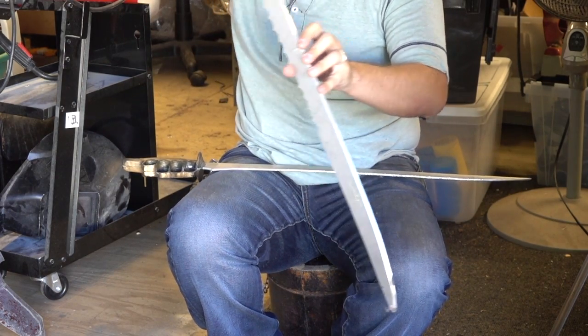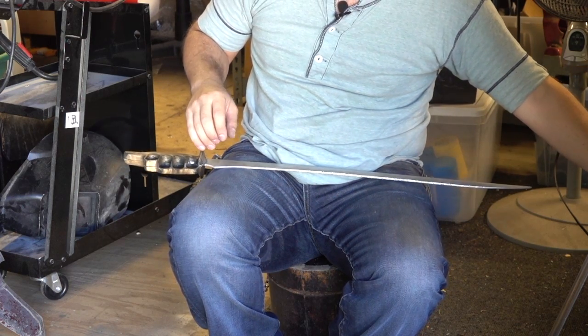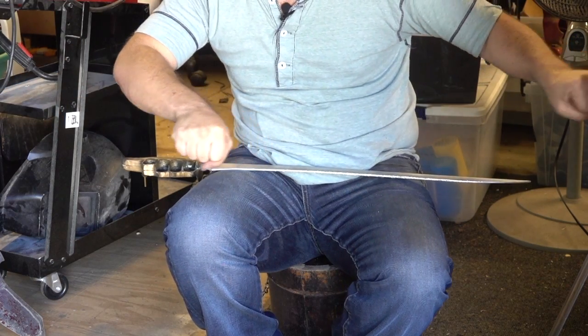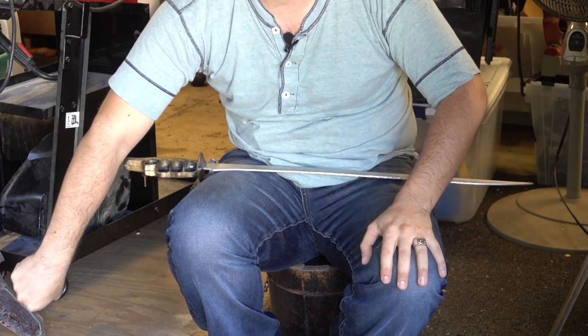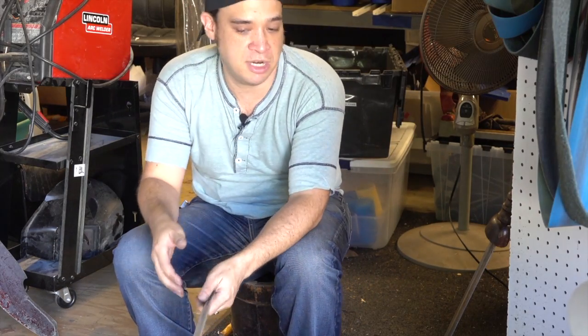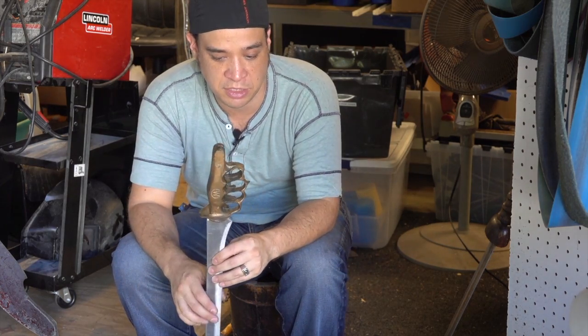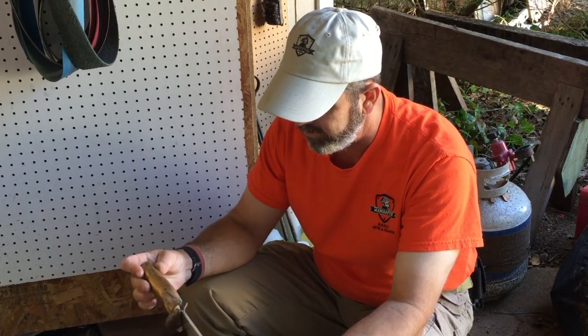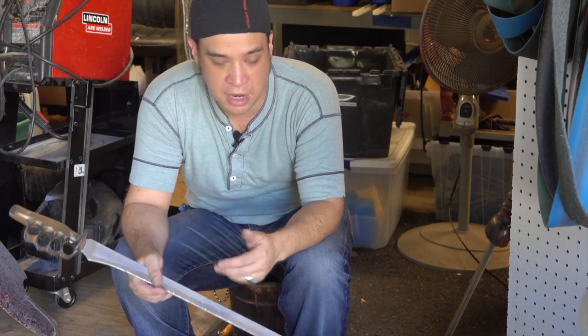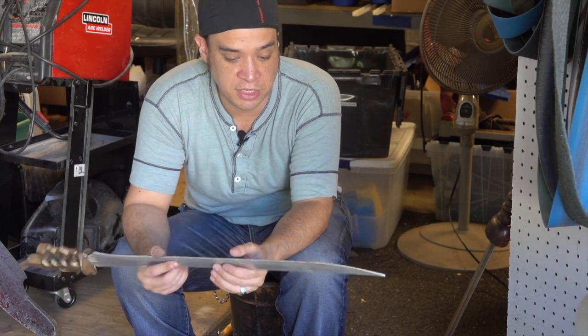So as long as you don't heat it up, when you're grinding it, you have to cold grind it. So you have to have a big vat of water. You make a pass, stick it in water. Cool to the touch. You work bare hands. But if you heat it up, then it just becomes like this. And how could you tell the difference just because you've handled it so much? Yeah, just from handling it, and how it reacts whenever you bend it, and how soft it is.